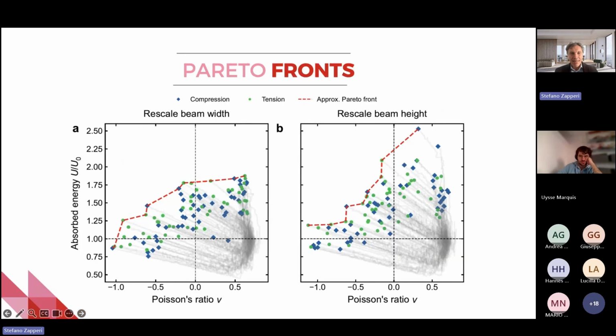And by changing this, you can identify a sort of front, which is the best you can get from these two properties. And okay, this we call the Pareto front. So depending on where you go, which weights more, you can go either on one side or on the other side. But still, you can get good compromises. Now, of course, this side is not very good because here Poisson ratio is positive. So you want to stay on that side. And here are two examples where you rescale. It's a technical fact. We want to keep the mass constant in this optimization, and this we do by rescaling the beam width or the beam height, and they give slightly different results.